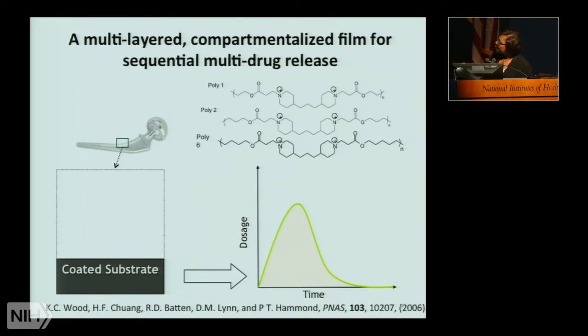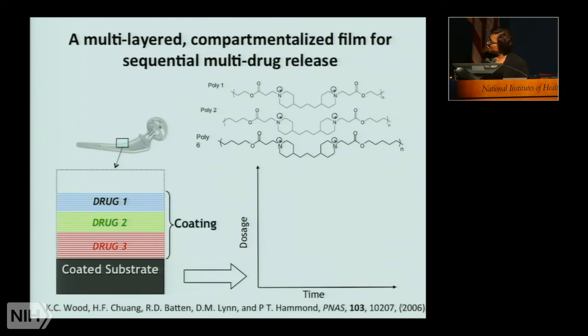On the other hand, with layer by layer, we can select a degradable polyion, like this polycation. This is a family of polybeta amino esters. The main point here is that they have positive charge and an ester group, which allows them to break down, and they're biocompatible. If we use something like this and layer it with a drug molecule that is charged, we can create thin films in which the drug is one of the components of the film. Now we've gone from loadings that are 1 or 2 weight% to loadings that are in the 10, 20, 30% range and can be as high as 50 weight%.